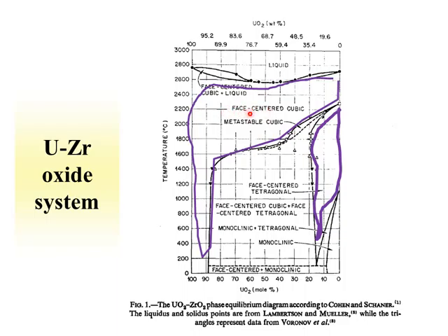So over here we'd have face-centered cubic structure dominating in this area. When we got to higher and higher amounts of zirconium, obviously more than you would see in nuclear fuel, you would have this face-centered tetragonal form dominating. You'd have a mixed phase here and then a monoclinic form here. Within this regime, at lower temperatures, we have two species formed.